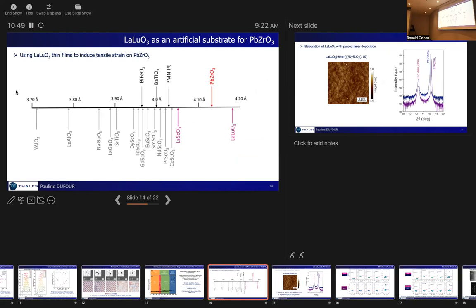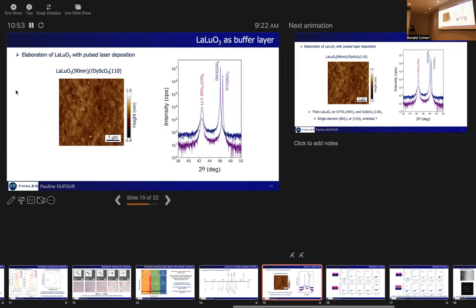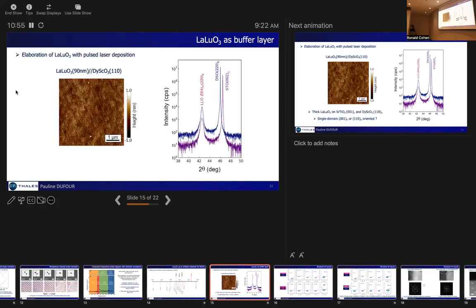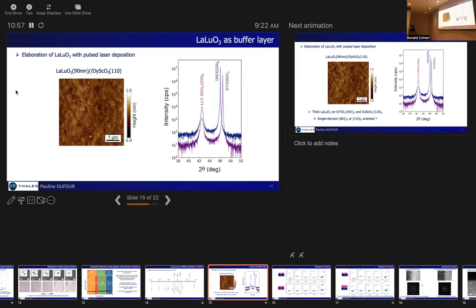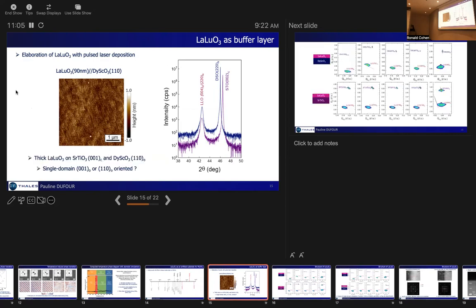So to induce tensile strain, we resorted to lanthanum lutetate that we elaborated with pulsed laser deposition. So we grew thick films of 90 nanometers on dysprosium scandate 110 oriented and strontium titanate 001. And we obtained flat surfaces with atomic steps, and structural characterization suggests that we have one single domain that can be either 001 or 110 oriented.